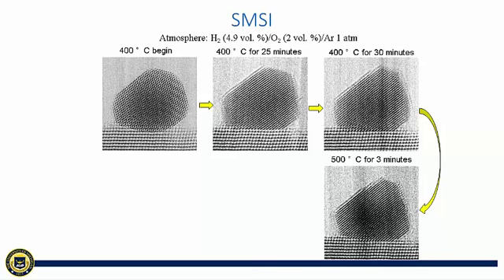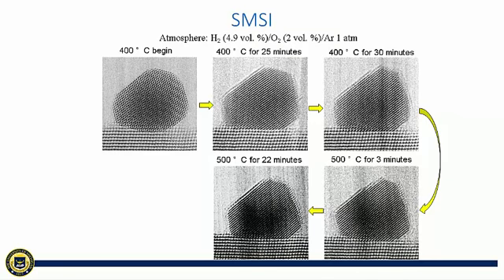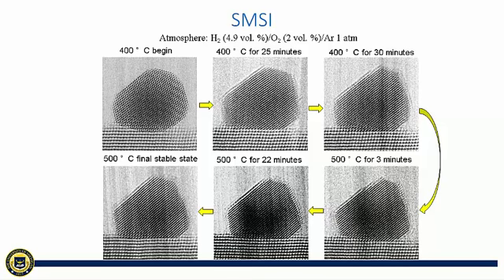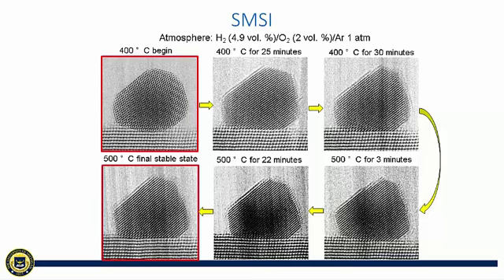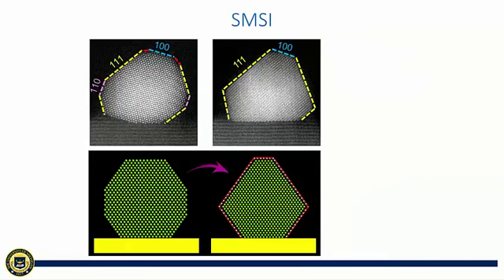And if we increase to 500 C, we can start to see step formation on the side of the particle, indicating the migration of surface atoms. And then it reheals. And this is the final state of the particle. If we compare the initial state with the final state, we can clearly see the shape change that happened during this process, and we want to have a more quantitative understanding of the shape change from a round particle to a faceted particle.